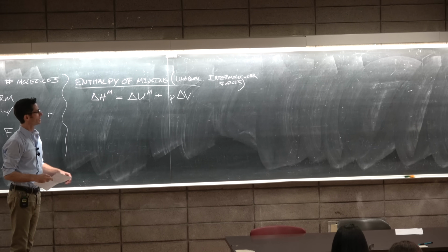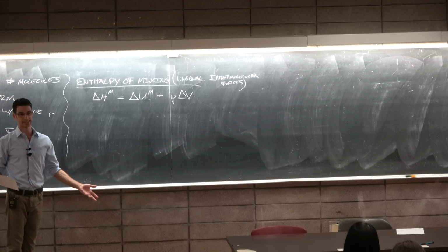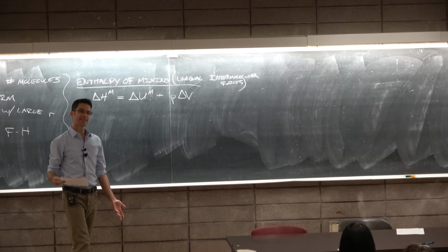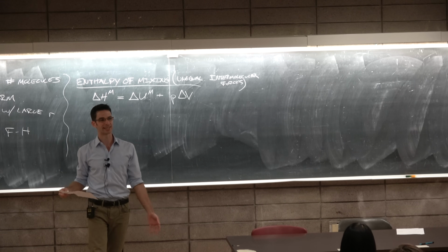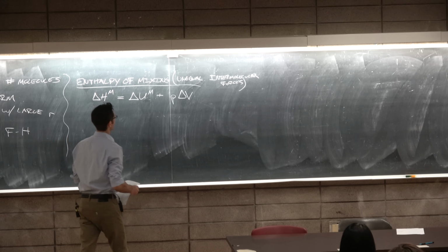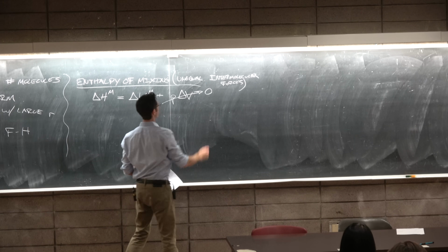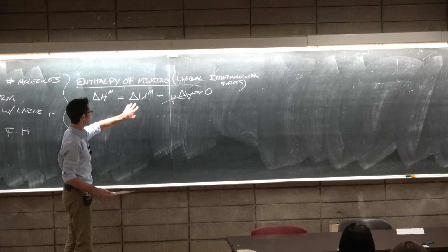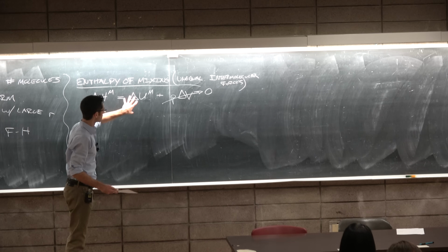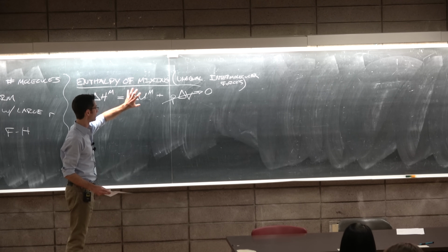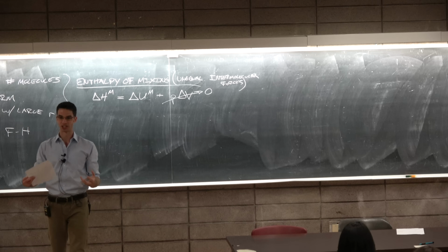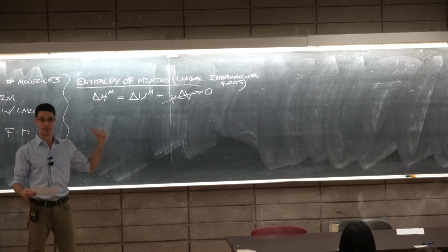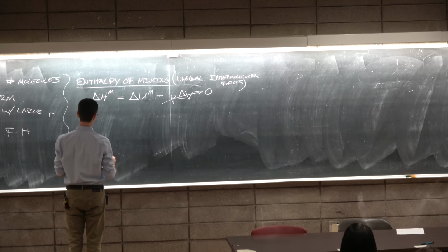Now, in chemical systems where we're just mixing stuff, there's usually a negligible change in volume. Incidentally, I think it's ethanol and water you mix together, the volume actually goes down. But we're going to forget that. The lattice is exactly the same size. So what I told you in last class is true for this model. The change in internal energy is just a change in the intermolecular forces, which manifests directly as the change in enthalpy from the unmixed states to the mixed states.